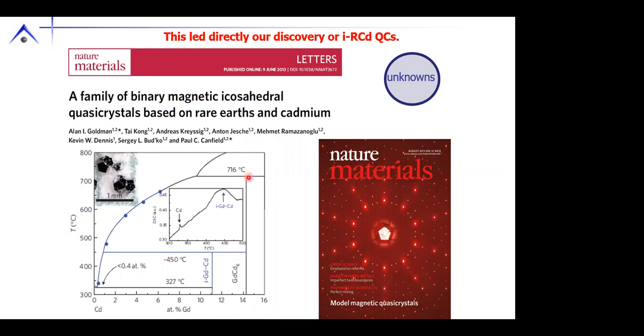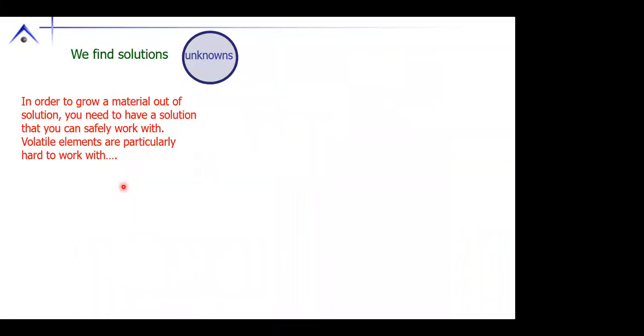And based on this, we were able to make sort of the audacious prediction that if we cool this slowly to low enough temperatures, we would probably grow the cadmium, Cd6, and get little hexagonal pimples on it as we entered into a hypothesized quasicrystalline phase, and indeed, that's what we found. All right, let me give you another example of unknown unknowns, okay?